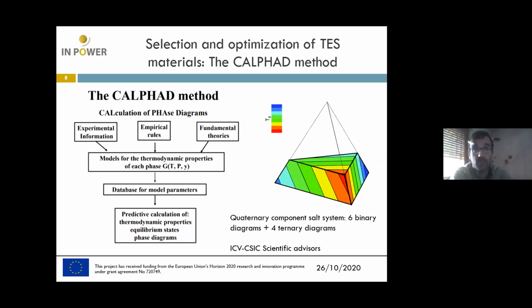To detect the best composition, we were always looking for the eutectic composition, that is, given any mixture of n components, the eutectic composition is the minimum temperature composition of all the systems. And it also behaves as a pure component. It's not like solar salt that, as you know, starts melting, but part of it remains solid. So a eutectic composition at melting temperature will all become liquid. So this is also useful in terms of local low temperatures that don't plug the system due to local solidifications, and it seems to be a good approach.